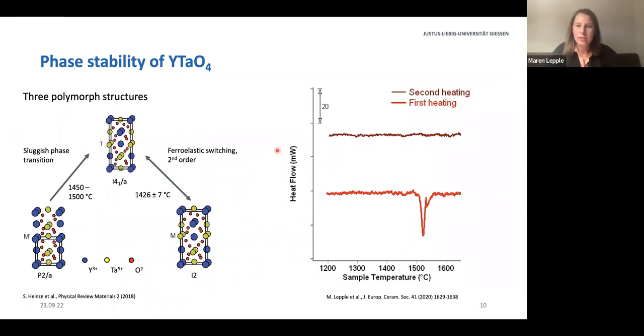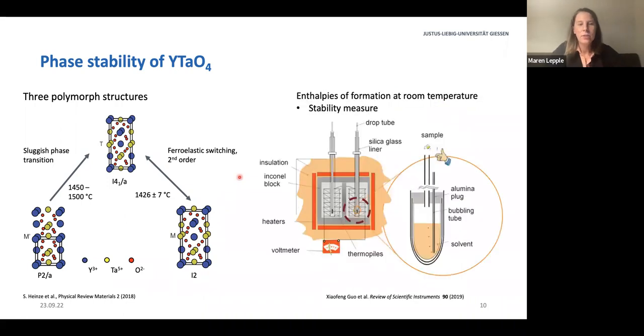And the thing was that, as you can also see here, when we were starting from the M' phase and heating the M' phase, for example, in a differential thermal analysis, we had one peak, so the phase transformation here to the tetragonal phase. However, on cooling, the tetragonal phase will not transform back to the M' phase, but will form the M phase. And then when you heat again, you will not see any signal anymore, because this M to T transition is a second order transition. So this was already reported in the literature, and we found the same when we did thermal analysis at UC Davis. So maybe naive Maren thought, oh well, we can investigate the stability very easily if we just measure the enthalpies of formation at room temperature, and then we can determine which of these two monoclinic phases is stable.